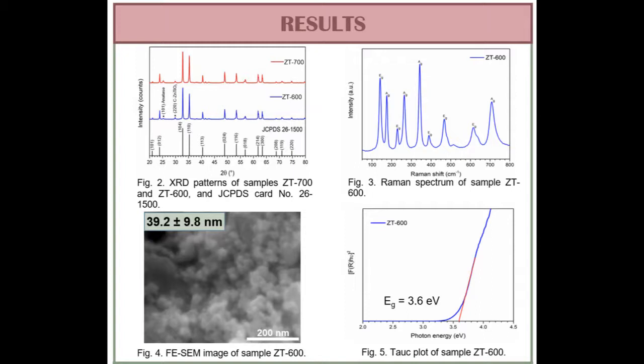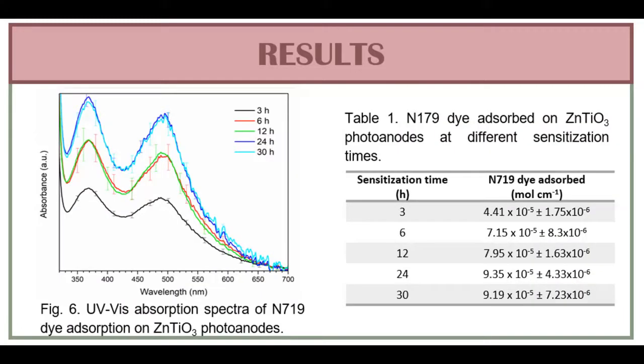The optoelectronic properties of our material have been characterized by diffuse reflectance spectroscopy, and the bandgap energy has been calculated with the Kubelka-Munk transform, obtaining a bandgap energy of 3.6 electron volts. Since the material exhibited adequate properties for its use as photoanode material, we conducted a study to evaluate the best sensitization time on the most commonly used and efficient DSSC dye, N719. Our study demonstrates that the material has reached its maximum dye loading at 24 hours, with a dye absorption of 9.35 × 10^-5 mol per centimeter.